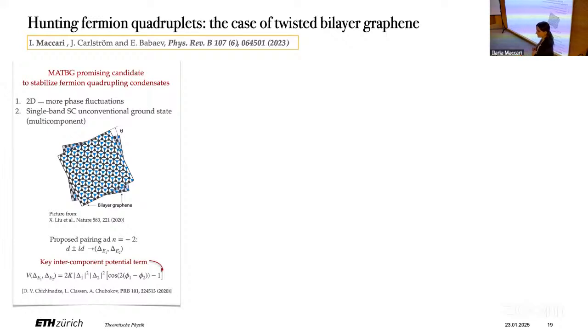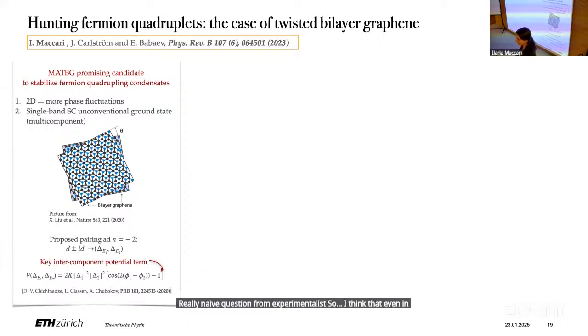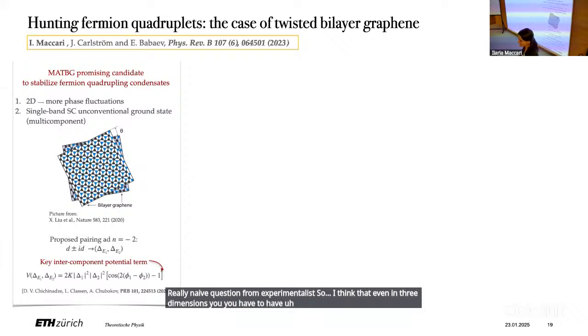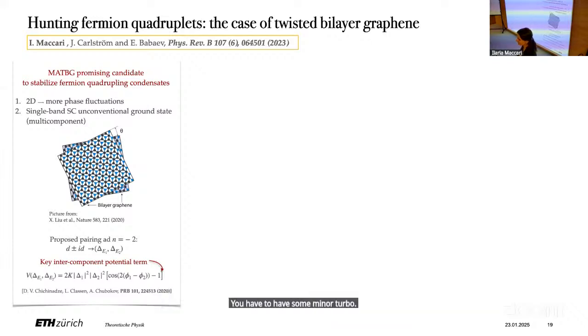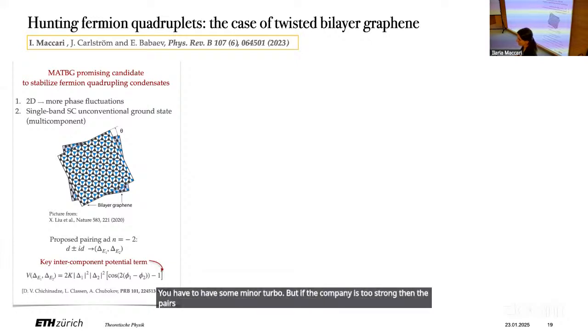Here's one really naive question from an experimentalist. I think that even in 3 dimensions, phase coherence is established when Cooper pairs are overlapping. You have to have some finite overlap. But if the coupling is too strong, then the pairs are too small and they don't overlap, so there is no superconductivity. Is this the reason why you need two components?